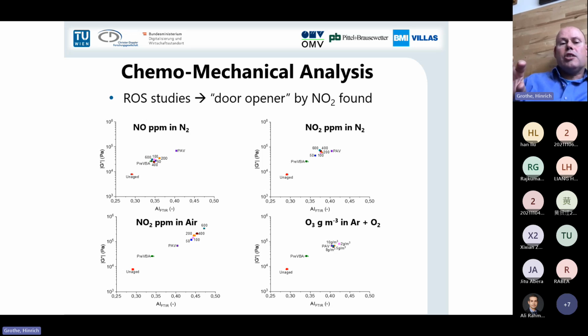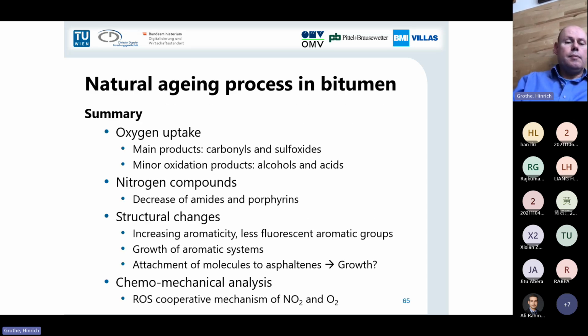So we imagine that the NO2 is something like a door opener. It reacts with our aromatic structure, and then the oxygen can go into that hole and further oxidize the organic material. And this is a very typical reaction known for polyaromatic systems. So just to summarize that a little bit, we have an oxygen uptake. We have as a product mainly carbonyls and sulfoxides. Minor products are alcohols and acids. Nitrogen compounds are amides and porphyrins.